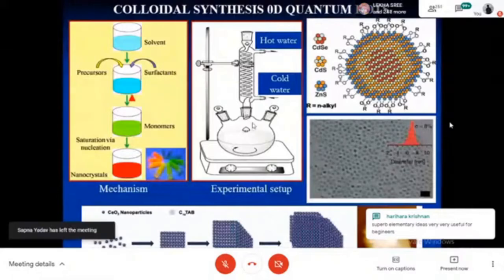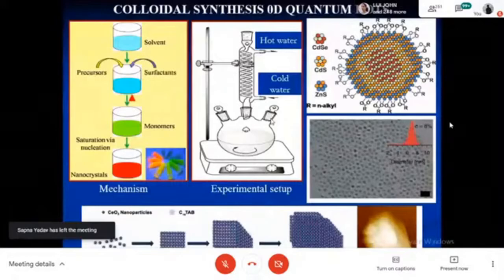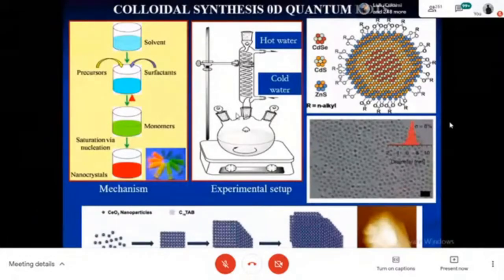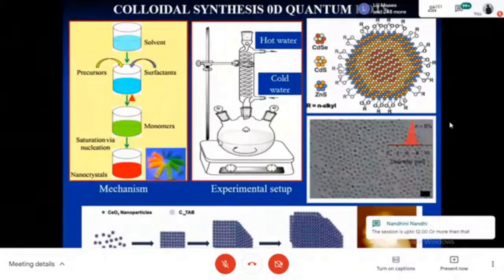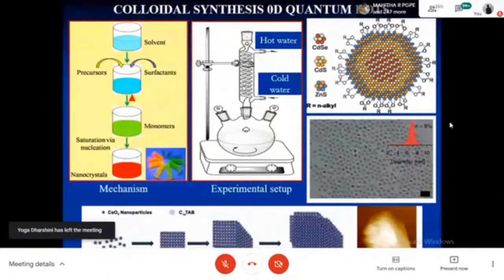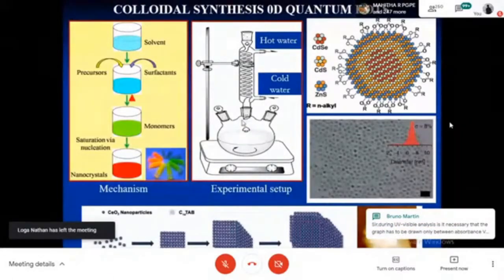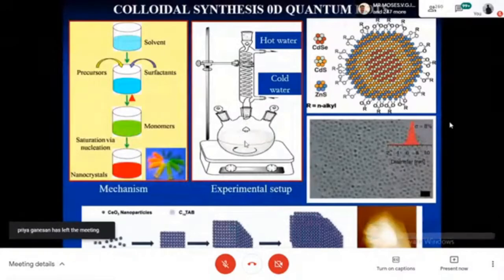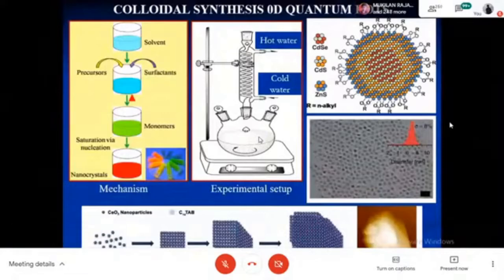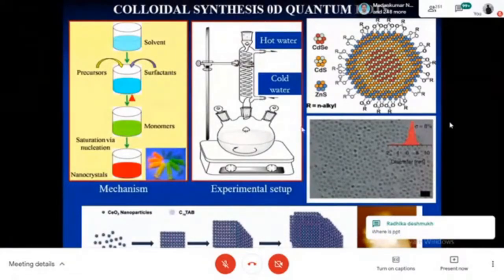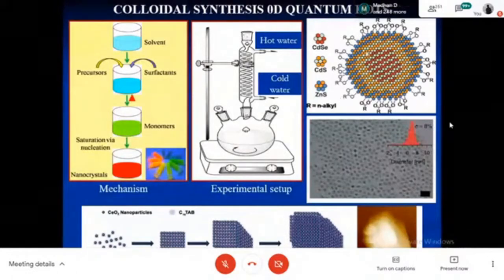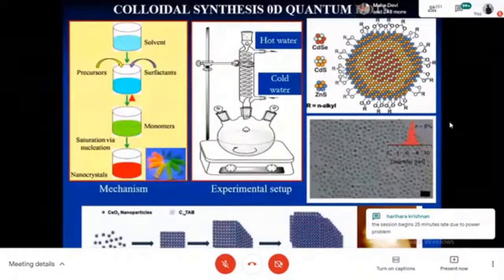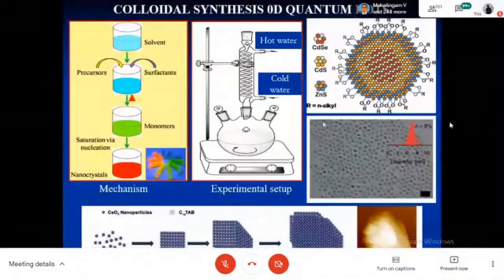And the colloidal synthesis has a very simple experimental apparatus where we have a 3-neck glass chamber, and this is heated with a heater, so that we have uniformity and homogeneity inside the chamber. And you allow cold water to hot water, so that we maintain the temperature properly. Then evaporation is induced at this stage, so that nucleation starts at the bottom, and then it grows to the level. And once it grows, we have the surfactant acting on the material to control the size. So the self-assembly process by colloidal synthesis follows this mechanism, where we can have binary materials like that, or we can also have ternary or quaternary compounds, and it involves very, very well-ordered structures by self-assembly process.